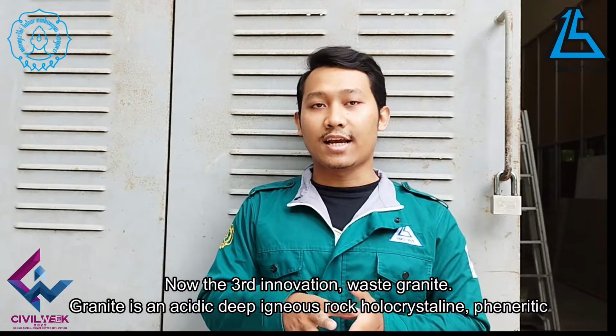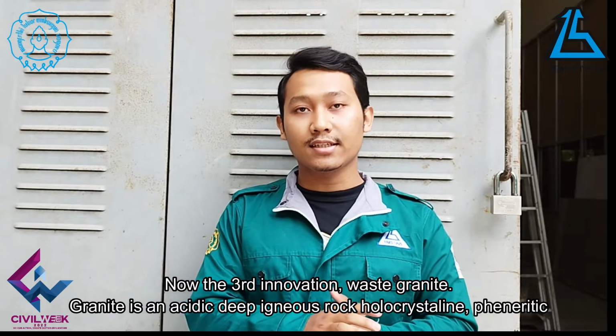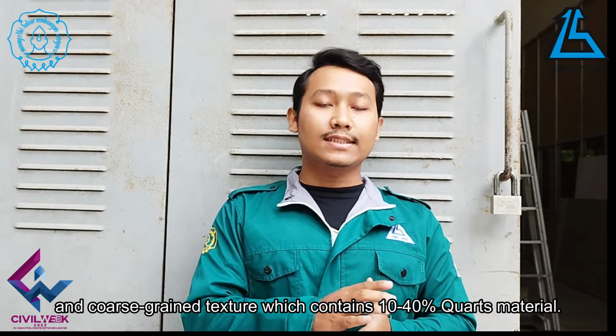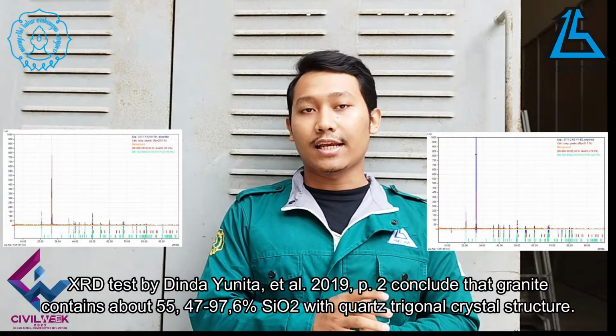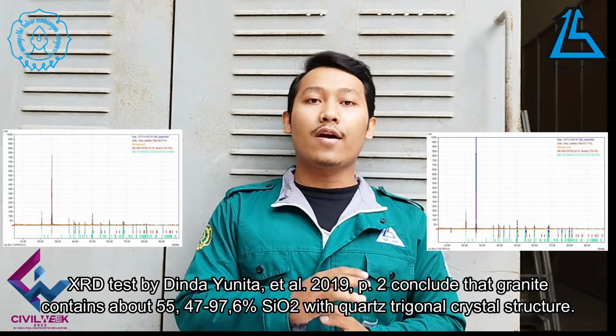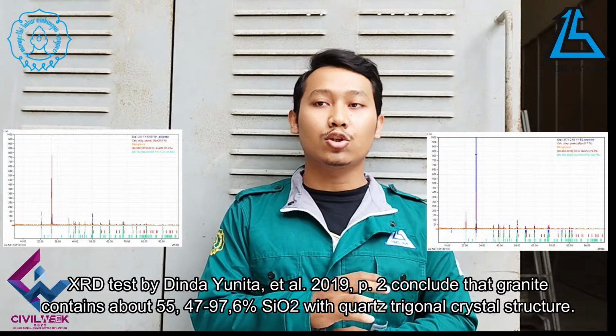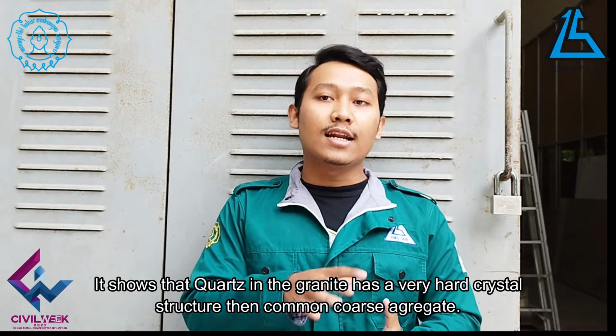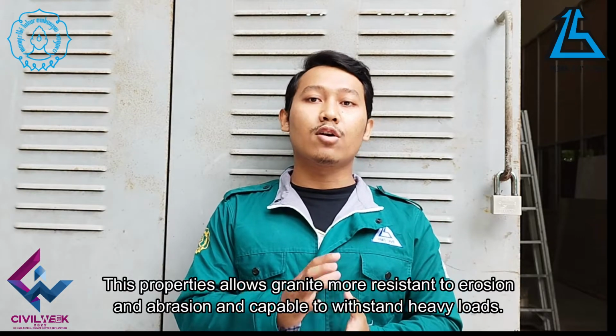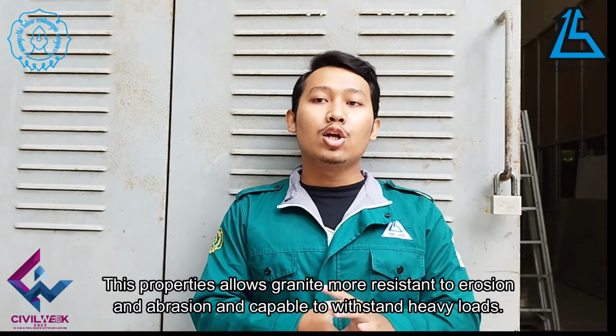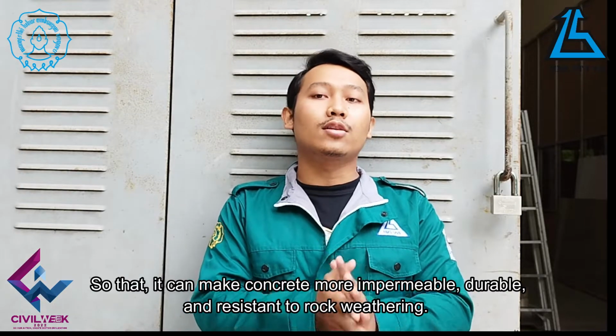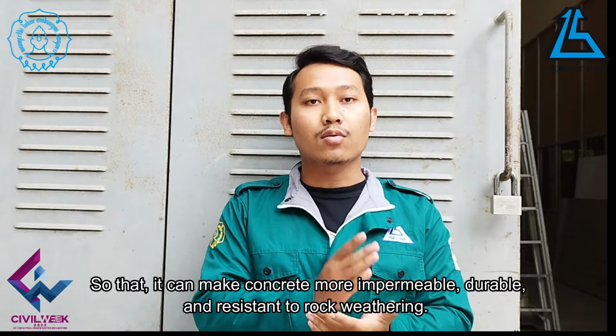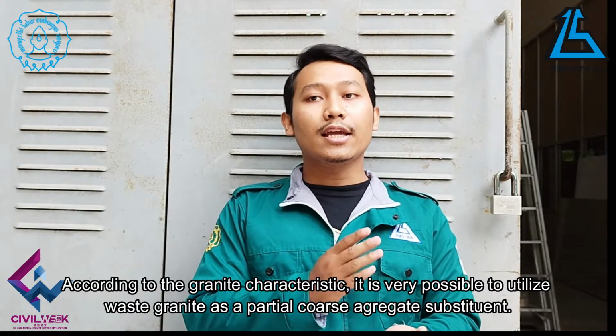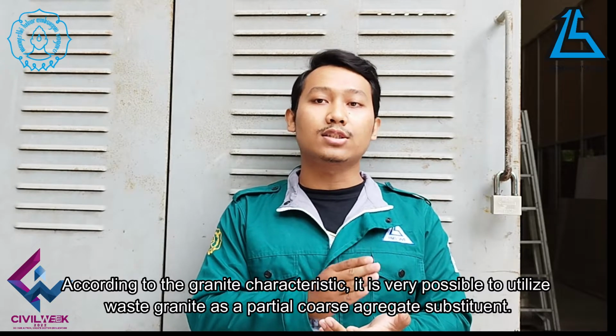Now the third innovation, waste granite. Granite is an acidic deep igneous rock, wholly crystalline, phaneritic and coarse grained texture, which contains 10 until 40% quartz materials. XRD test by Dinda Yunita 2019 concluded that granites contain about 55.47 until 97.6% SiO2 with quartz trigonal crystal structure. It shows that the quartz in the granite has a harder crystal structure than common coarse aggregate. These properties allow granite to be more resistant to erosion and abrasion and capable of withstanding heavy loads, so that it can make concrete more impermeable, durable, and resistant to rock weathering. According to the granite characteristics, it is very possible to utilize waste granite as a partial coarse aggregate substituent.